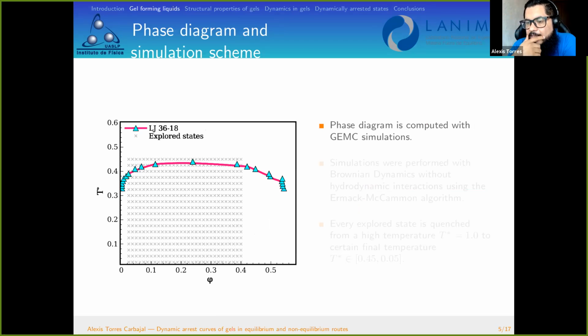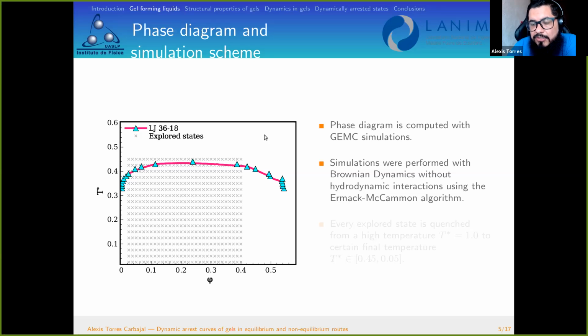In the literature, we found many studies about these gels, and many of them are based primarily on systems with pure short-range attraction, and eventually, in the last couple of years, there are some studies that incorporate the repulsive part. In this sense, we take the pure attractive short-range fluid as a reference. We determine its phase diagram in order to know the states in which the system is above the phase coexistence.